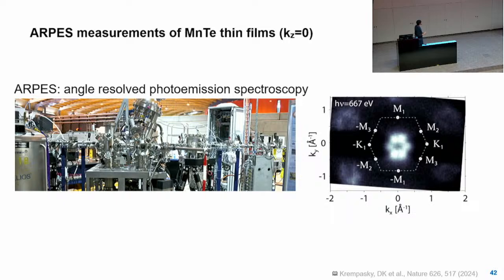That's synchrotron light. And this synchrotron light is a very powerful tool in condensed matter research, because it can give light in a very large wavelength range. And what we need here is something like ultraviolet light to X-ray light to investigate these materials. So this light comes from these large rings. These rings are typically hundreds of meters in diameter. And then it comes to one of these pipes here. It's already somewhat preconditioned, and then it goes into one of these chambers where your sample is. The photon hits your sample, and it excites some electrons. Those are coming out, and you analyze their energy and their direction, and from that you can calculate back to the dispersion of the system.